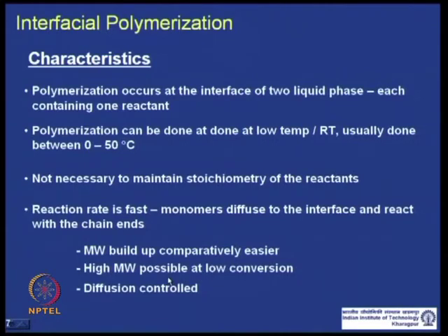And as the monomers get added at the end of the chain, high molecular weight is even possible at low conversion, unlike the normal polycondensation or step polymerization process. And because the diffusion is slower compared to the actual polymerization reaction, these polymerization reactions are often diffusion controlled.